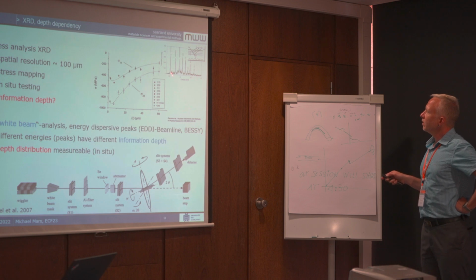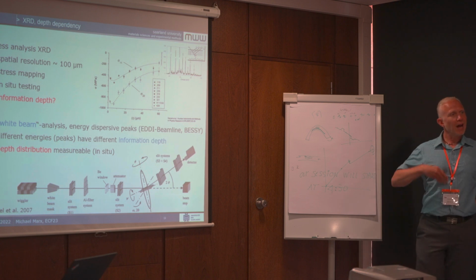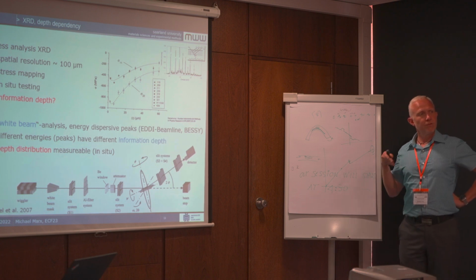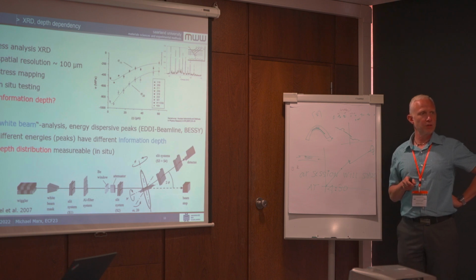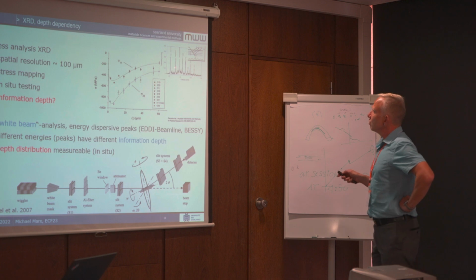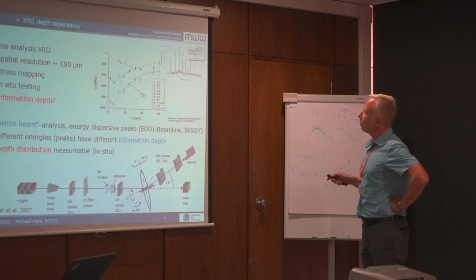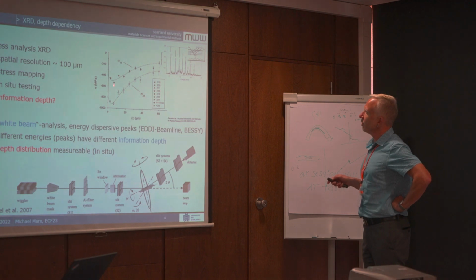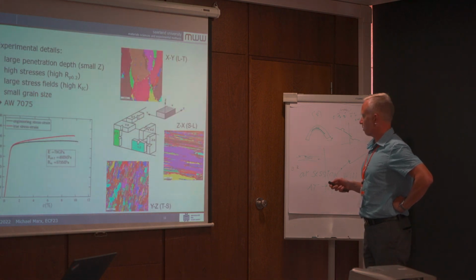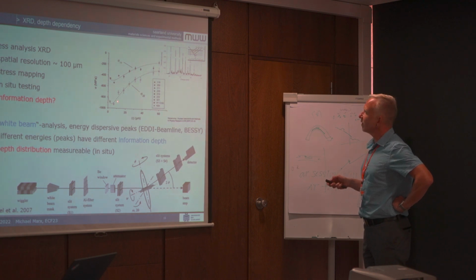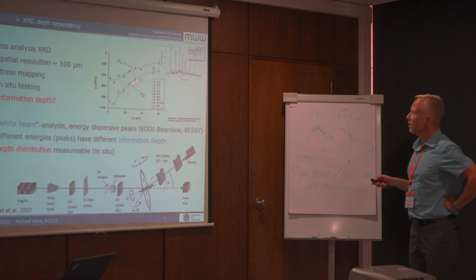Well, in XRD you have the peaks for the different planes in your crystal, and these peaks you get at different energies. And a higher energy means you have a higher information depth because of the absorption of the X-rays in your specimen. For the lower index peaks, you have only a small information depth, and then the information depth increases with the higher order X-ray peaks.